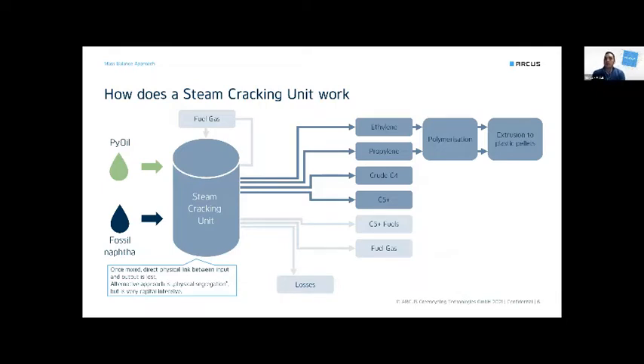Ben already talked about the mass balance approach, and for pyrolysis, mass balance is fundamental. There is no other way to recover recycled feedstock. If you look at mixed plastic waste, what should happen to pyrolysis oil? It should go into established infrastructure from the petchem industry, like steam cracking, which is the source of ethylene and propylene used for the production of PE and PP. There is only one way to convert pyrolysis oil, and it is to co-feed with fossil naphtha.